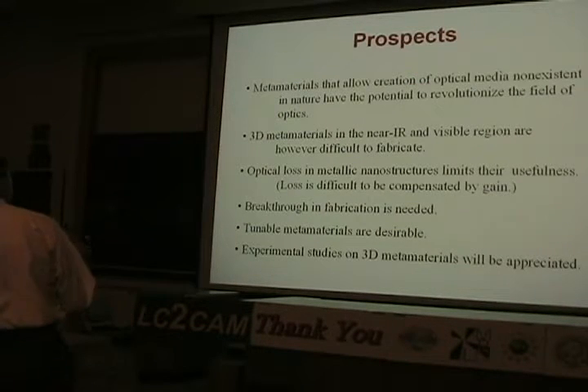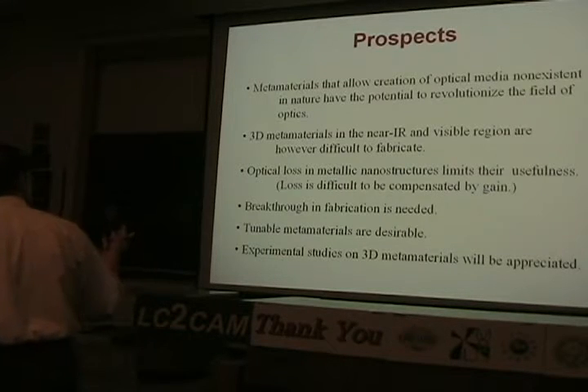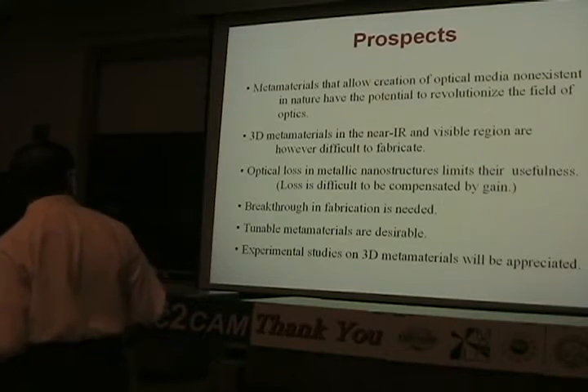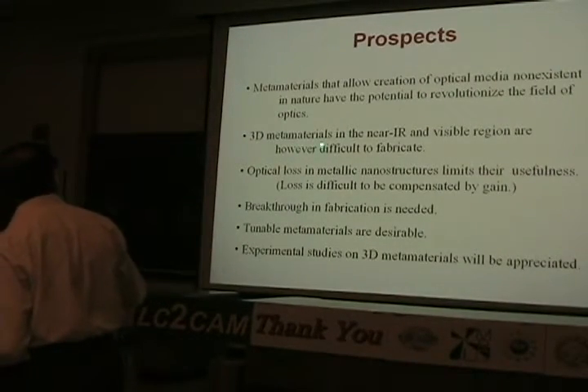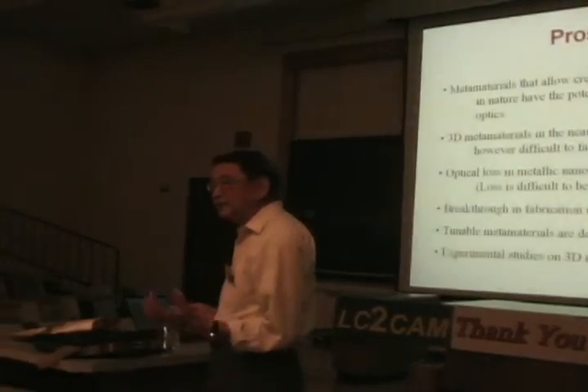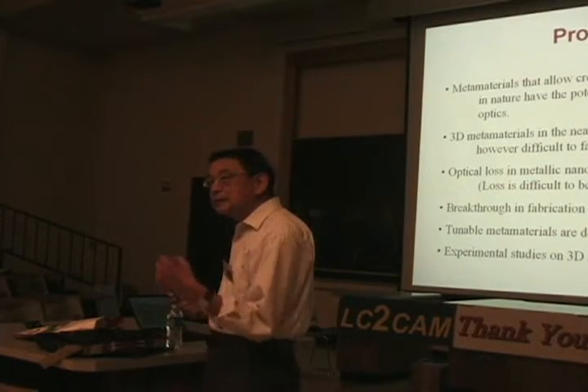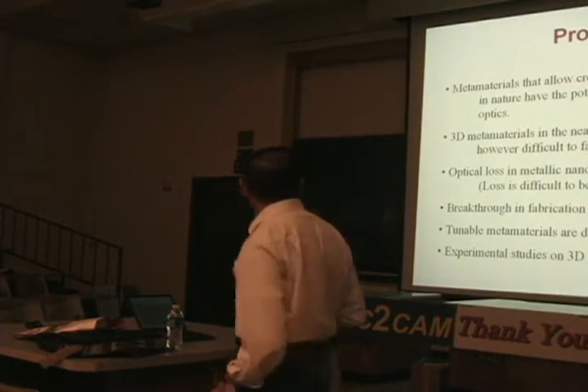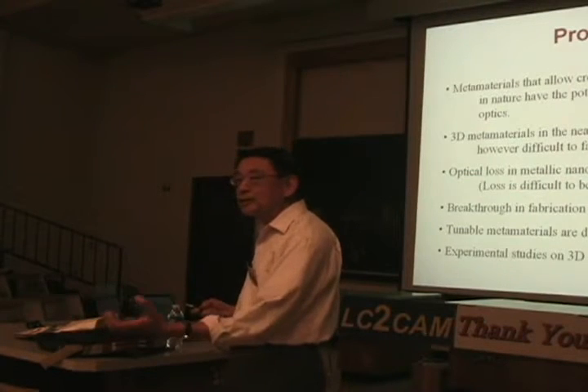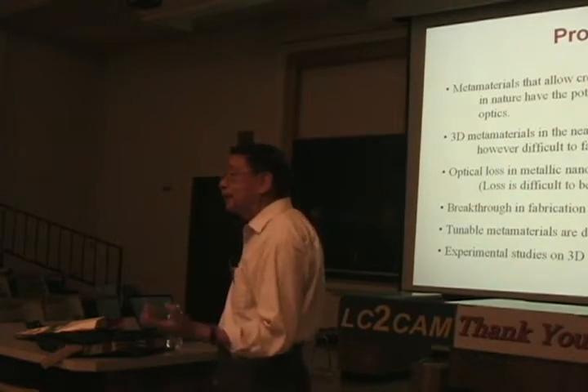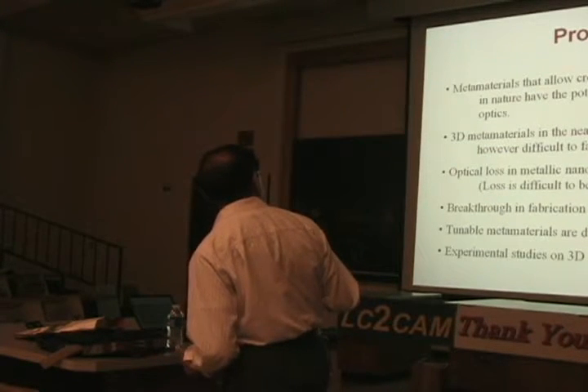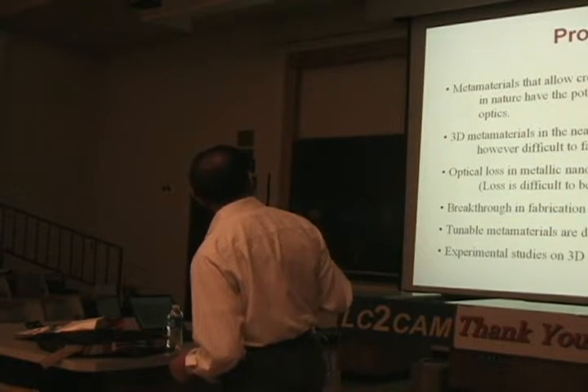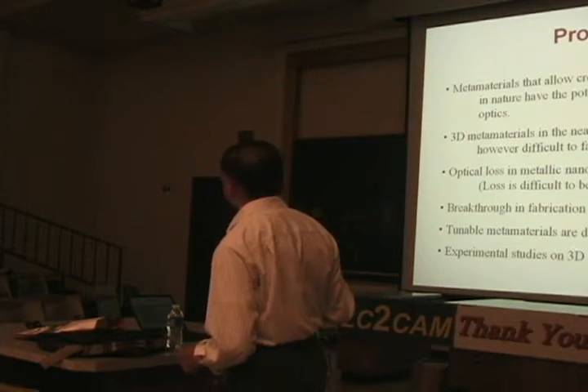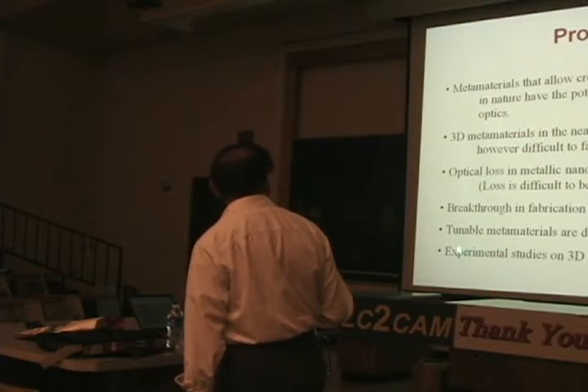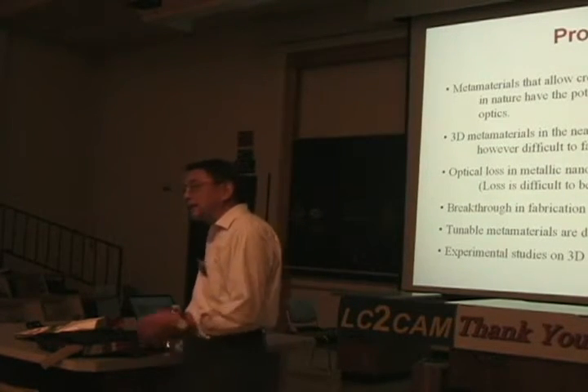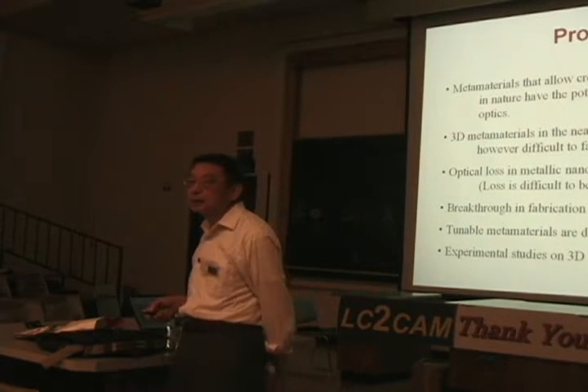We have the metamaterials that can give you new materials that are non-existent in nature, and therefore it has the potential to revolutionize the field of optics. But what we really need is 3D metamaterials, and that's very difficult to fabricate. The other problem is we use metals, so optical loss is extremely strong, and if we cannot compensate the loss or eliminate the loss, we will be in trouble in applications. And so people use the idea of compensating the loss by gain. But in any case, we need a breakthrough in fabrication. And tunable metamaterials are really desirable. And we also, of course, appreciate experimental studies on the 3D metamaterials in the optical range. Thank you very much.